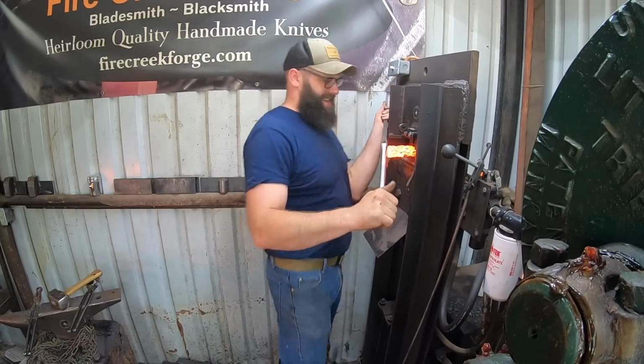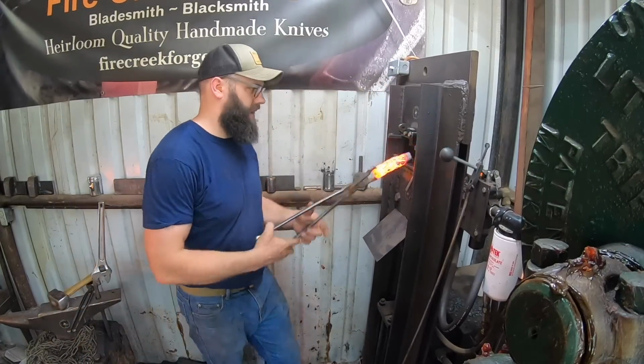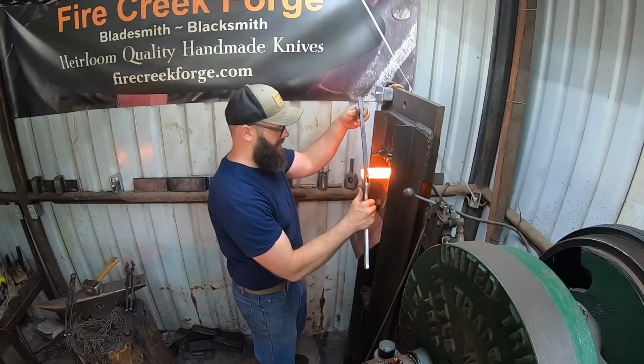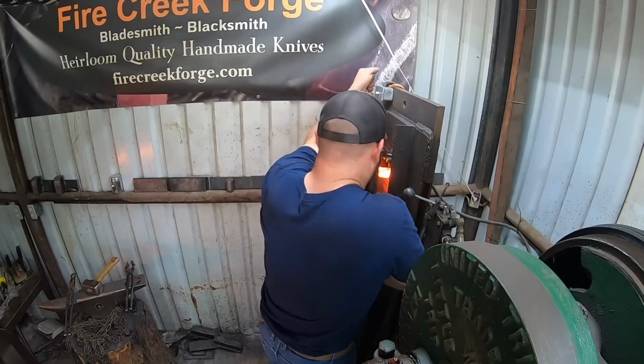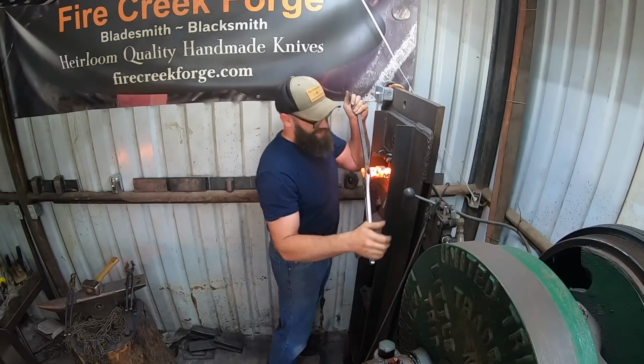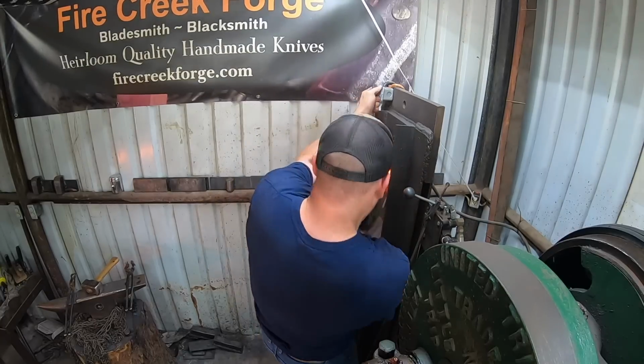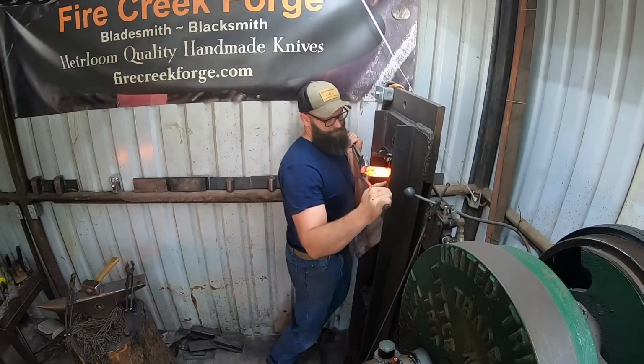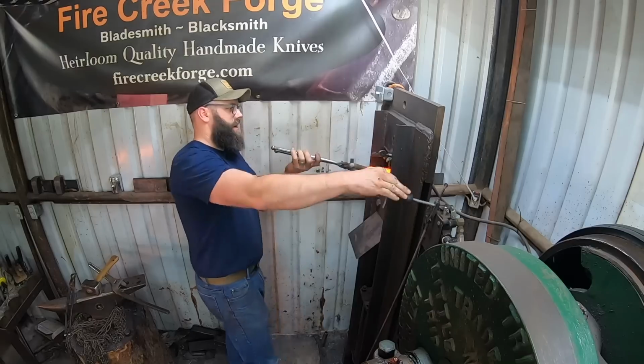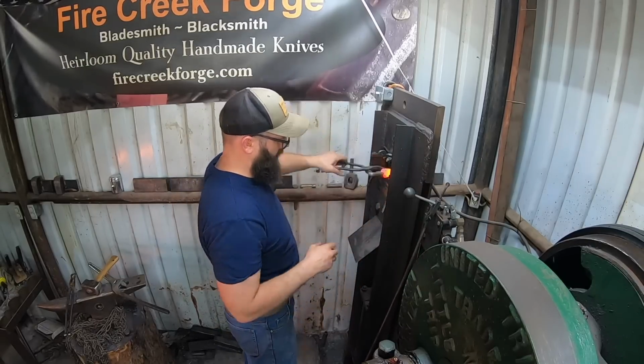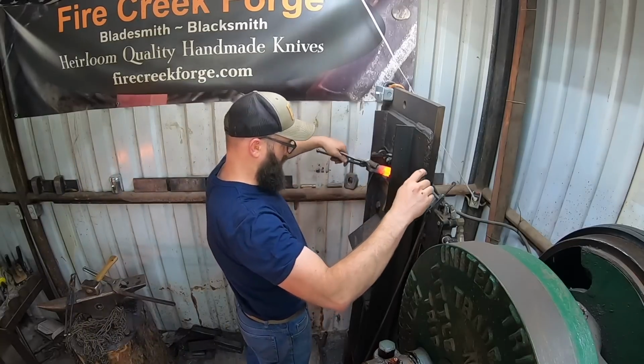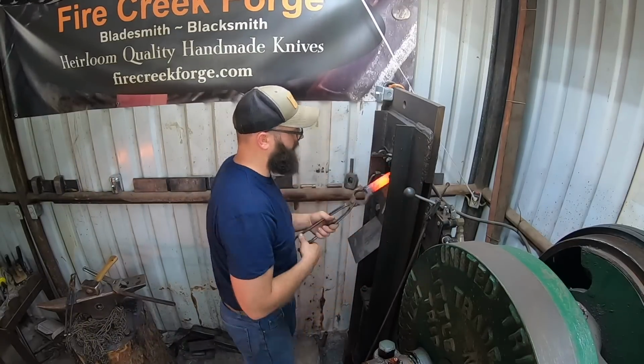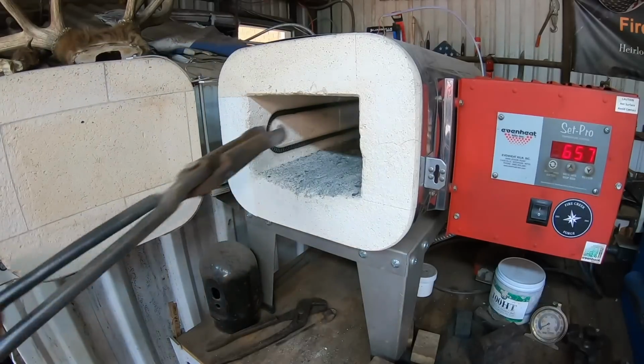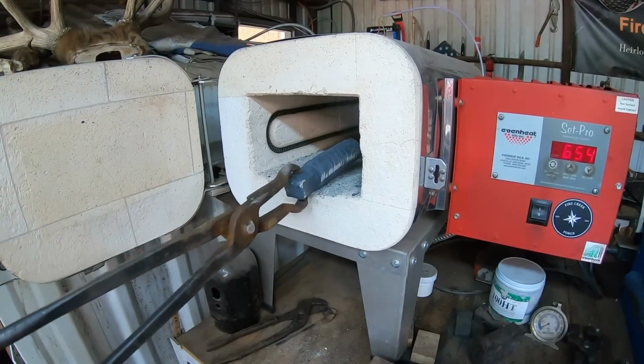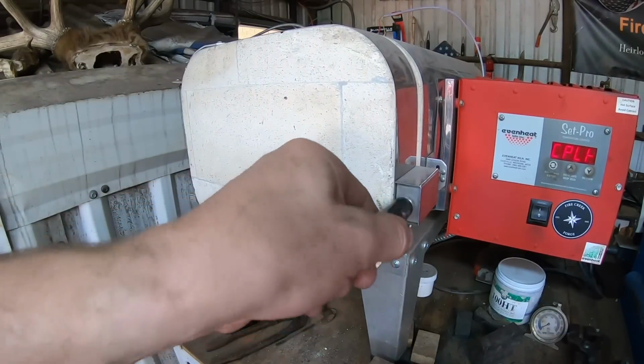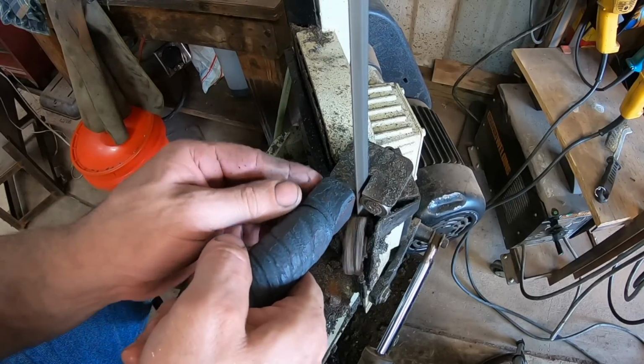But I was able to work at it little by little and return it to the forge multiple times to keep it at a good heat, and we were able to get the job done. As soon as it started to cool down a little bit and stiffen up, you weren't going to do much twisting at all. So it took a little while, but I got the amount of twists on it that I wanted. Didn't count, but a good tight twist. And pressed it out a little bit here and there as we progressed, so it's a little bit longer than when we started. But I needed to keep that wide enough to accomplish the pattern that I'm going with.